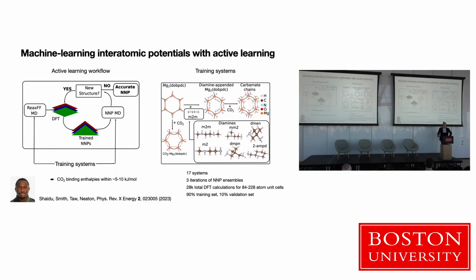We also had to identify an exchange correlation functional that gave us good accuracy. So that's a very important part. Our ground truth is critical, and we're looking for 5 kilojoules per mole, which is actually quite stringent. And you can pick functionals that don't get that. So part of this is always the ground truth. We use an active learning scheme. One nice thing about these structures is that even though they have a large number of atoms, for anything our MLIP generates, we can always do a static DFT calculation and check its energy. And if it's sufficiently different, we can add it back and retrain.